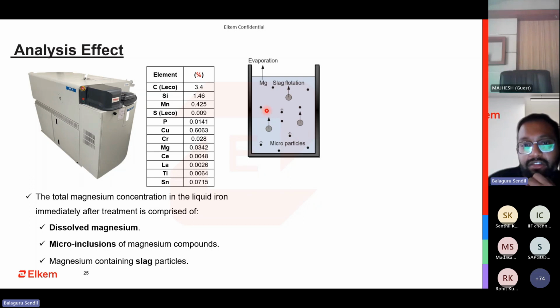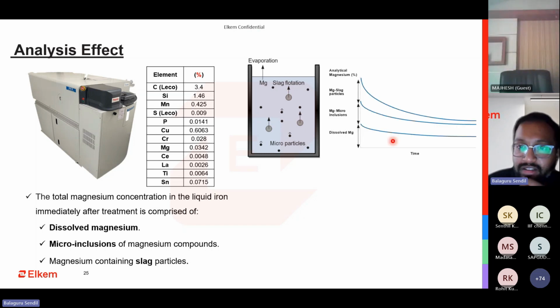And then the magnesium that is free. Why is it free? Because it doesn't have enough sulfur, or it has so much sulfur that it just keeps reacting here and then floating out. It is just evaporating out. So if you look at the amount of time, the dissolved Mg is much more stable with time. The Mg that is with micro inclusions is also quite stable. It takes a lot of time for these micro inclusion particles to float out. They will be there only. So it is the amount of excess Mg that keeps floating up.